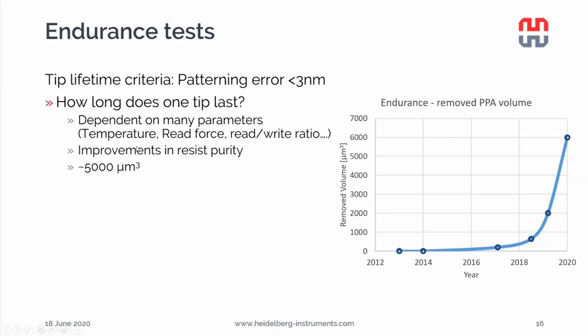By improving this resist purity in this Eurostars project and even further, we were actually able to improve this patterning performance by quite a lot. We started off in 2013 with about 1 cubic micrometer of removed material until the tip had to be thrown out. And now we're at over 5,000 cubic microns. So this is quite an improvement over the years. And you see the curve goes up, and we hope to improve this value even more. But for most of you, 5,000 cubic microns is probably not a number that you can relate to easily.